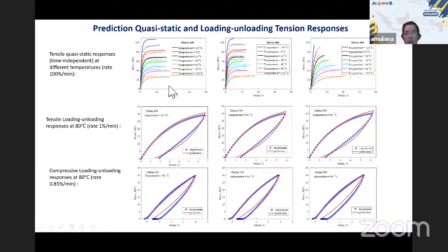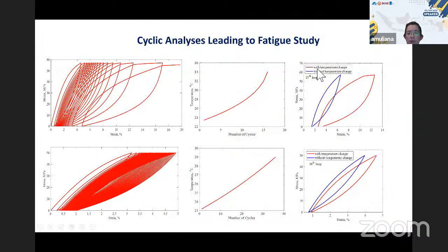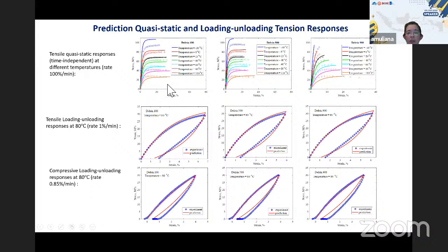Now this is for the quasi-static tension until failure, again for 4 different types of Delrin and at different temperatures. Same thing, the solid line is for the model and the symbols are for the experiment. Now I also show you the loading, unloading. So this is loading and unloading response under tension at high temperature, 80 Celsius, while the bottom one is loading, unloading under compression.